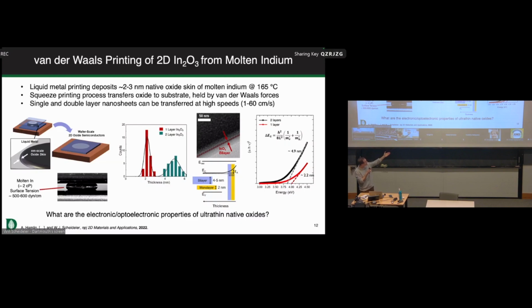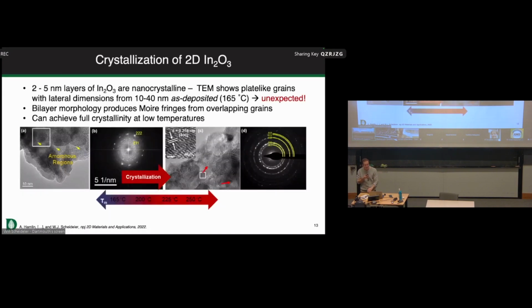So one example of how that manifests is if you measure the UV vis absorption of this material. As you make it thinner, it shifts the band gap to a higher energy. So this is one of the signs that we typically interpret to mean that we're exhibiting some kind of quantum confinement. And if you look, for example, at the Bohr radius, this is like a homework problem from a materials course. We've essentially thinned it down so it's approximately equal to the Bohr radius in this material. So it's thin enough to exhibit these interesting effects.